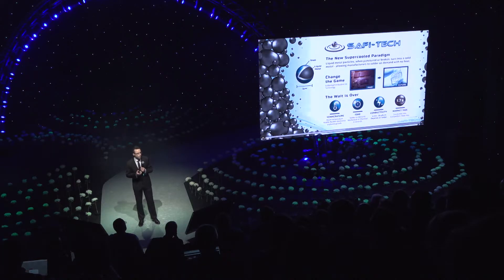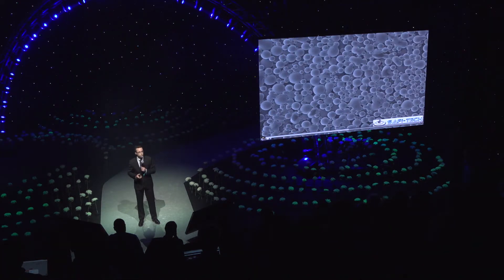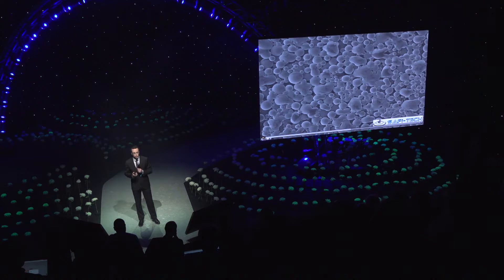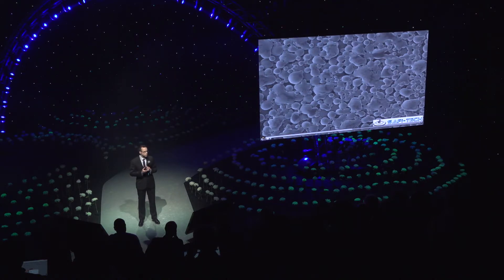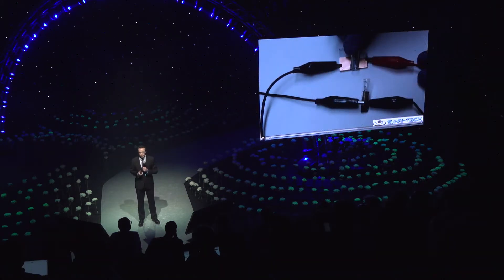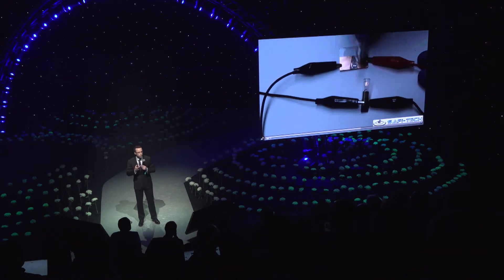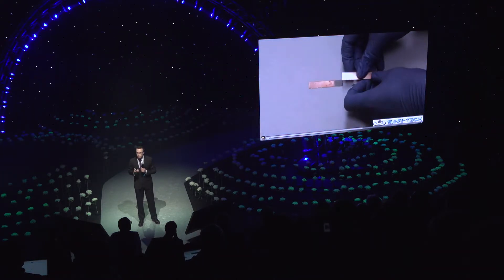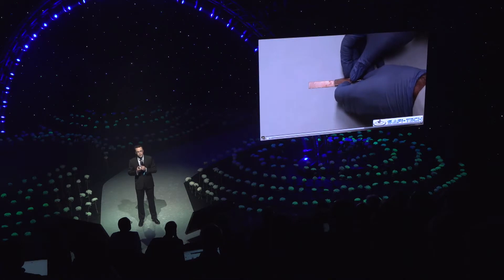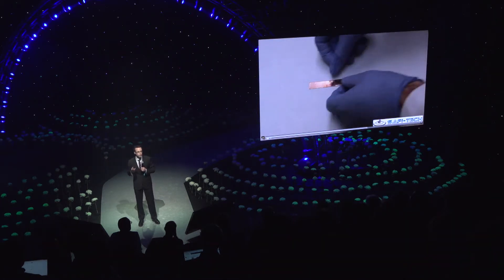From a scientific point of view, they're microparticles in the supercooled state. Here are some videos of the technology in action. Supercooling means that at normal temperatures — like room temperature — that metal really should be a solid, but because of our technology we put a little coating on them that protects them from the outside world and keeps them in that state until you want to use it. This changes the game for electronics manufacturers because they can now solder using solder metals on demand without heat.